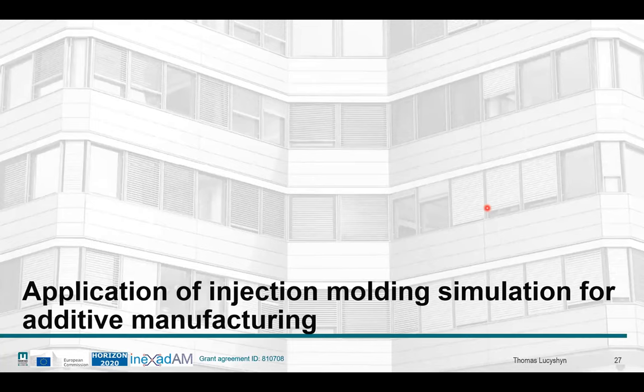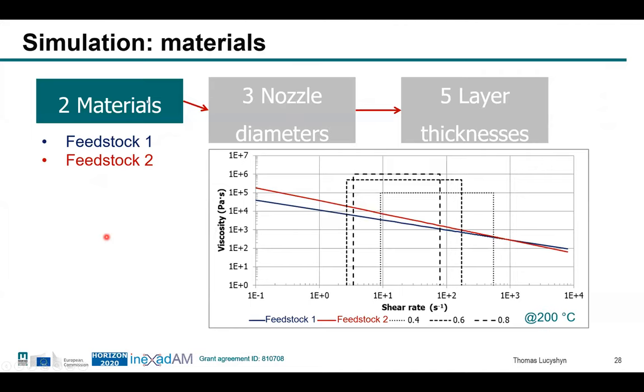Okay, so this is all about injection molding, but then we tried to see if we can kind of misuse the simulation also for simulating parts of a die, of a nozzle, of a fused deposition, so FDM process. So we had a look at two different materials, so two feedstocks, also once again powder injection molding feedstocks with different viscosity behavior. So viscosity over shear rate for two different materials, feedstock one, feedstock two.